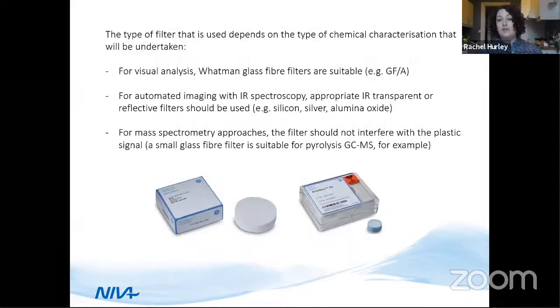The type of filter that you should use for your microplastic analysis will depend on what type of visual analysis and chemical characterization you plan to undertake later on. For example, if you plan to perform visual analysis prior to chemical characterization, such as FTIR, we use Whatman glass fiber filters, and these are very commonly used. Here at NIVA, we prefer to use the GFA type, and we typically use a diameter of 47 millimeters. This provides a large area for observing the particles and has a light background for identifying and documenting the different particle types. With the GFAs, the fiber weave is actually quite tight, so it's easier to pick the particles from the filter for subsequent chemical characterization.